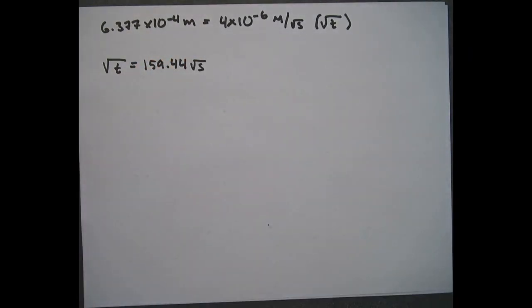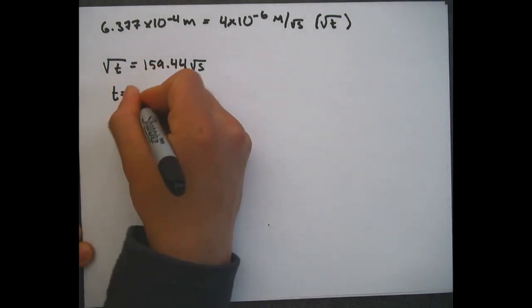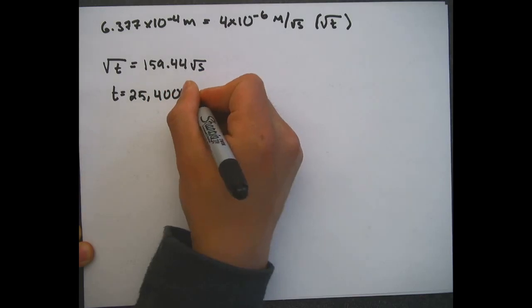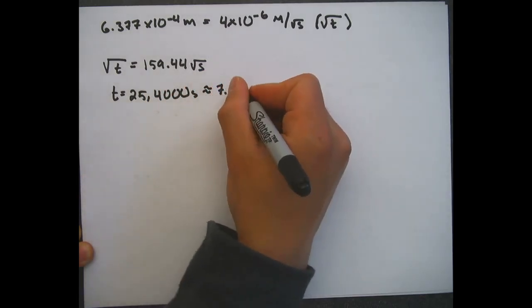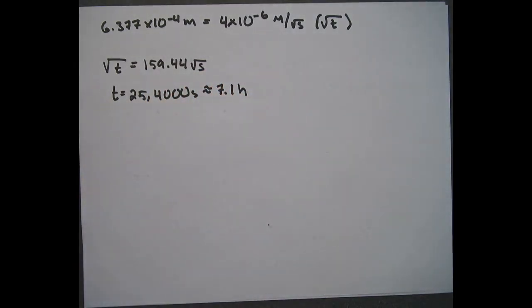Solving for t, we get the square root of t equals 159.44 square root of seconds. Now squaring both sides, we see that t equals 25,400 seconds, which is roughly 7.1 hours. I noticed when I wrote this, I made a mistake. It should be 25,400. I added an extra zero by accident.